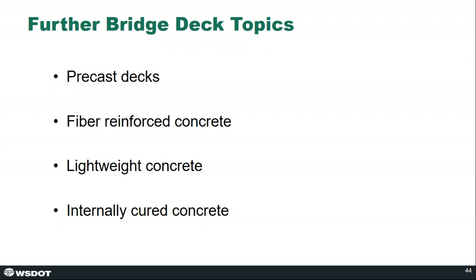And another avenue for potentially more durability is internally cured concrete. This is the inclusion of saturated lightweight aggregates into the mix, and the water that these aggregates absorb is slowly released into the concrete as it hydrates. So it's a way to maintain uniform hydration and extend the effective cure after your curing systems have been removed.